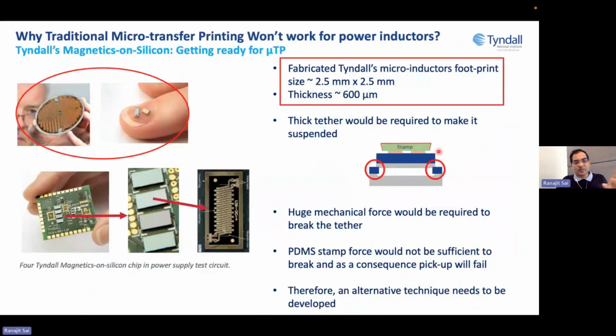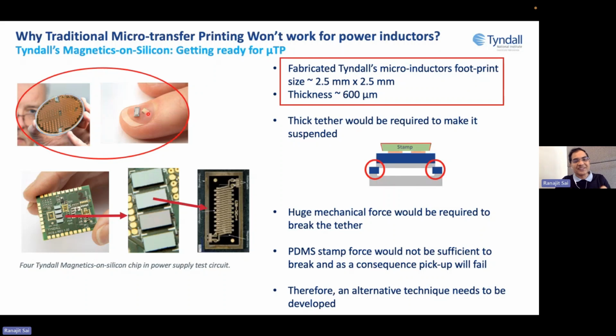The micro transfer printing is a very popular process. So we have inductors, and these inductors are of this size, and we have these micro transfer printed devices here, and you could see that these sizes are not too small, though it looks small with respect to the hand, but they are not very small for micro transfer printing. Micro transfer printing as a technology was developed for photonic devices, and they are much smaller. So the standard micro transfer printing process won't work for our devices.